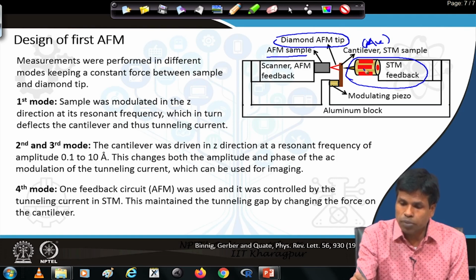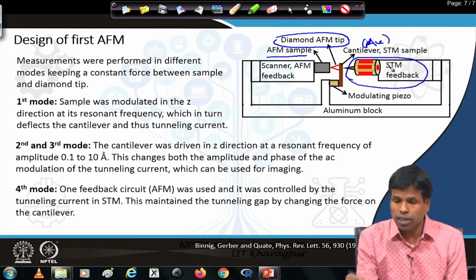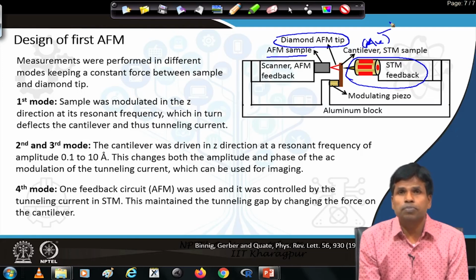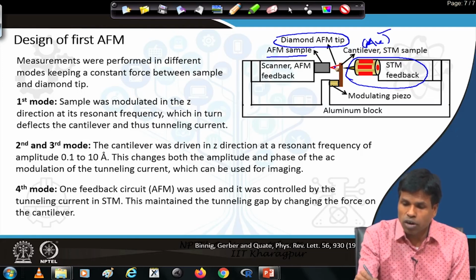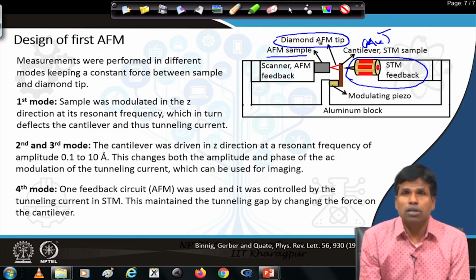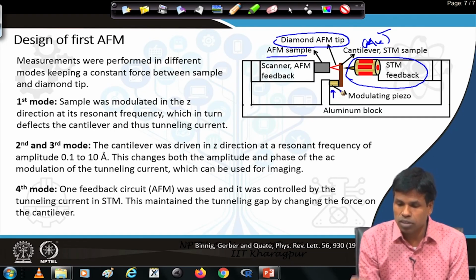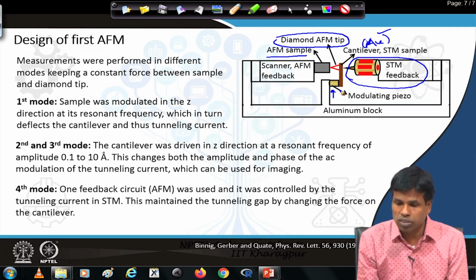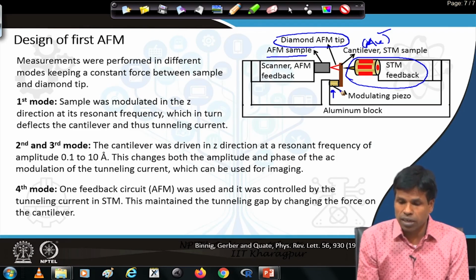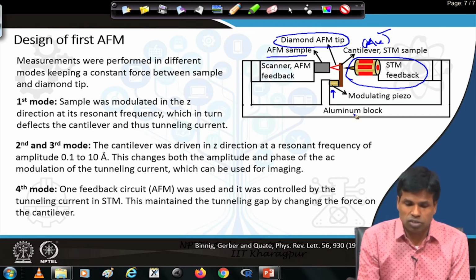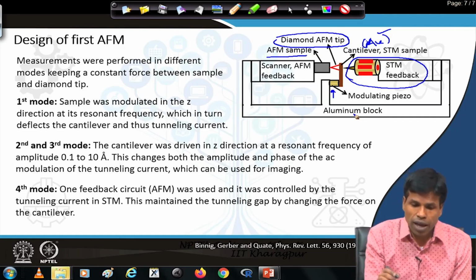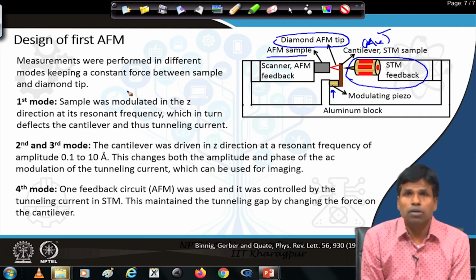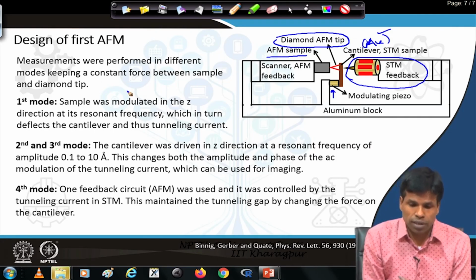Now, because STM measures the tunneling current, the cantilever is made of gold, but on the gold, at one end of the cantilever, the diamond tip is fixed. Then we have a modulating piezo here to control the movements of the cantilever in the x, y, z direction, and it is placed on an aluminum block. They have measured in different modes; there are 4 different modes they have demonstrated.